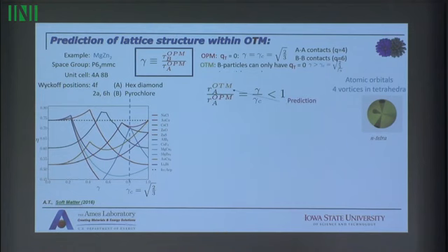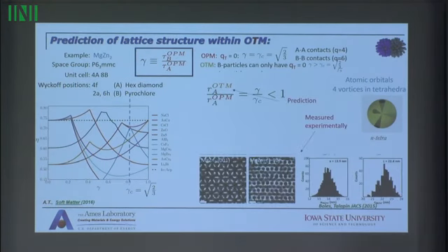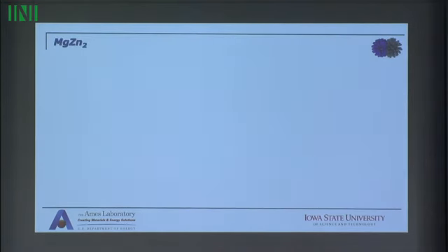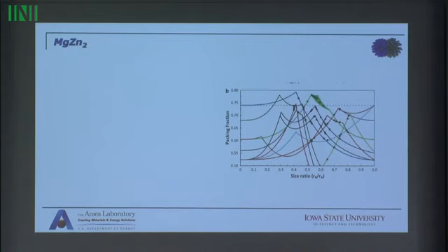And now you can go and compare with the experiment, because this is the magnesium zinc 2, these are electron microscopy images. You can plot the lattice constants, and then you can also tell what is the actual lattice constant. So what are we doing here? Well, we are considering, first of all, this branch. This is magnesium zinc 2. The first thing we notice is that the experiments are only on the left side of the curve. What that means is that if we had vortices for the small particles, then we would have experiments on this side, but there are none. So that is a first qualitative thing that is in agreement with our observation.